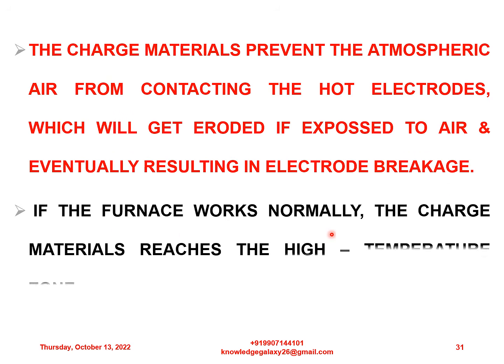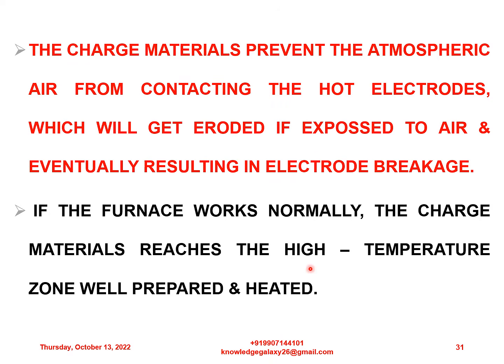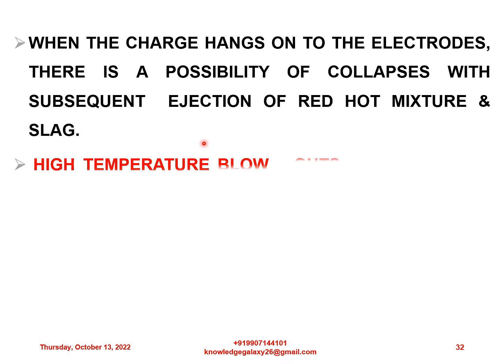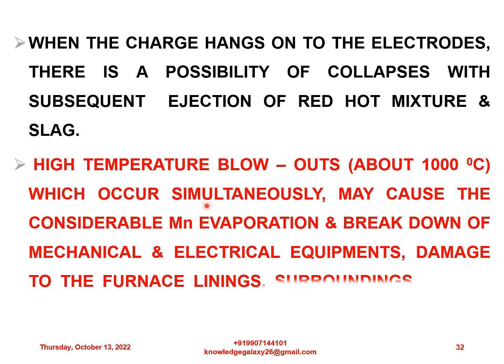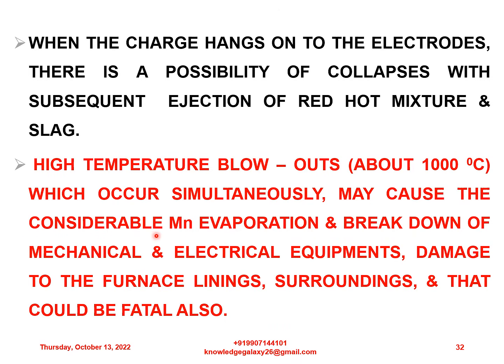If the furnace works normally, the charged materials reach the high temperature zone well prepared and heated. When the charge hangs onto the electrodes, there is a possibility of collapses with subsequent ejection of red hot mixtures and slag. High temperature blowouts, about 1000 degrees Celsius, which occur simultaneously, may cause considerable manganese evaporation and breakdown of mechanical and electrical equipment, and damage to the furnace lining and surroundings, and that could be fatal also.